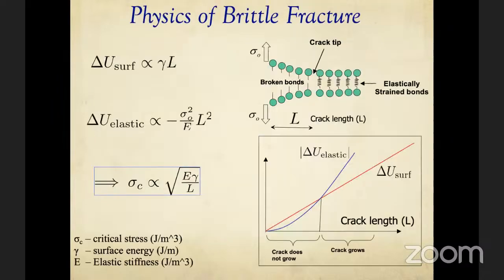So it turns out, again, the interesting thing here is these aircraft were not supposed to crash, but they had cracks that exceeded these lengths based on the material they were built from. And what would cause the stress to go higher than this? The fact that the portholes, the windows, were square. And so from that point on, they also started designing windows to be oval, with blunter tips, which would then reduce the stress around the window so that it would always stay lower than this so-called Griffith stress.